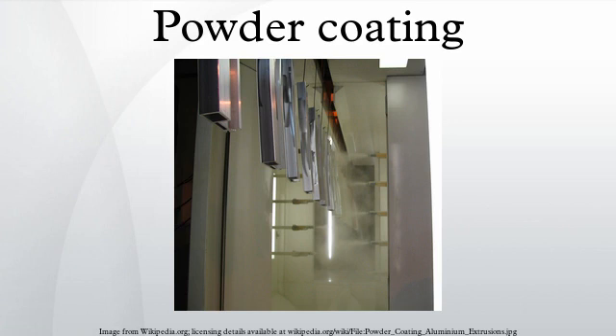Curing: when a thermoset powder is exposed to elevated temperature, it begins to melt, flows out, and then chemically reacts to form a higher molecular weight polymer in a network-like structure. This cure process, called cross-linking, requires a certain temperature for a certain length of time in order to reach full cure and establish the full film properties for which the material was designed. Normally the powders cure at 200 degrees Celsius for 10 minutes. The curing schedule could vary according to the manufacturer's specifications.